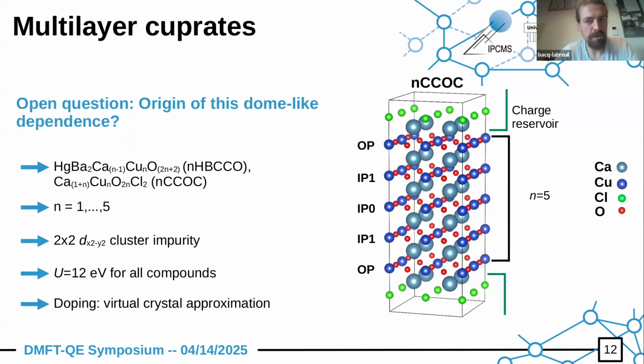Okay, so we'll study two families. I will mostly talk about this NCCOC, which is shown here on the right. It's made of calcium, copper, oxygen, and chlorine. And we also studied another one based on mercury. We look at the crystal structure from n equal 1 to n equal 5. We use a 2x2 cluster impurity, the x² minus y² orbital. We set a U of 12 electron volts for all the compounds, so we have only one fixed parameter for all the calculations. And we'll see that with only one fixed parameter, we can actually get a lot of knowledge about the physics of this system. And as far as doping is concerned, we use the virtual crystal approximation to ease the treatment a little bit.